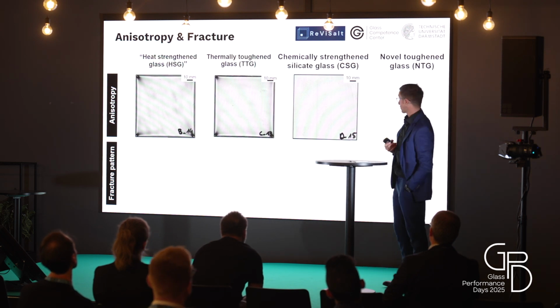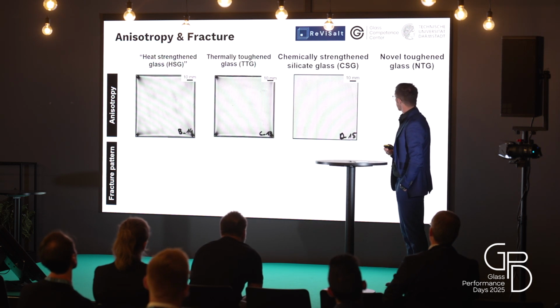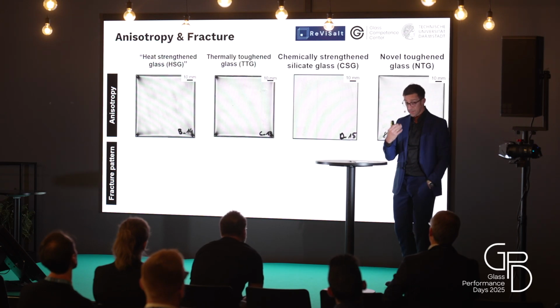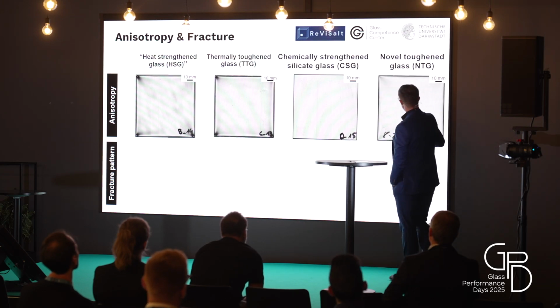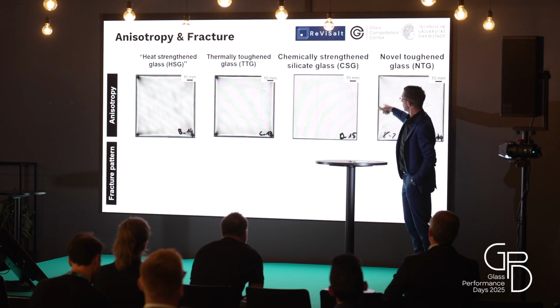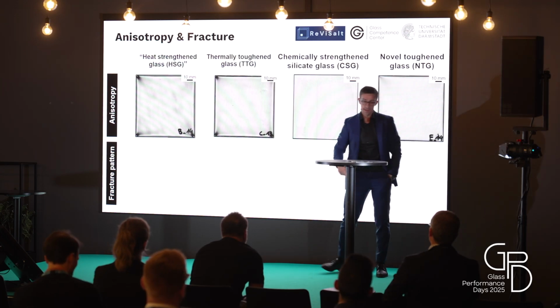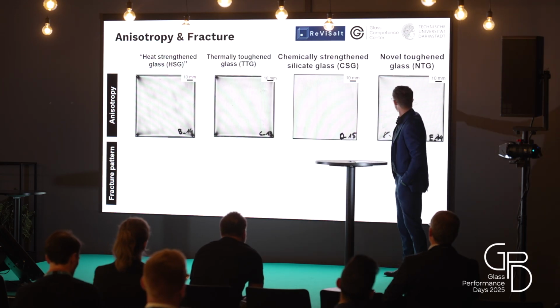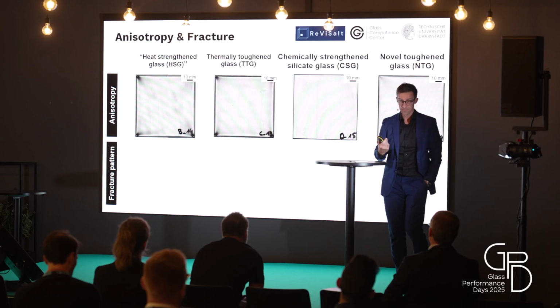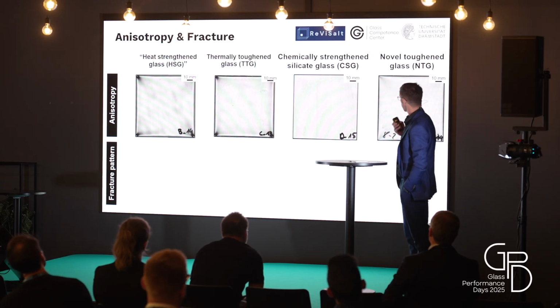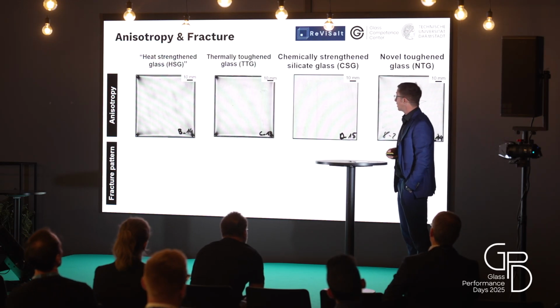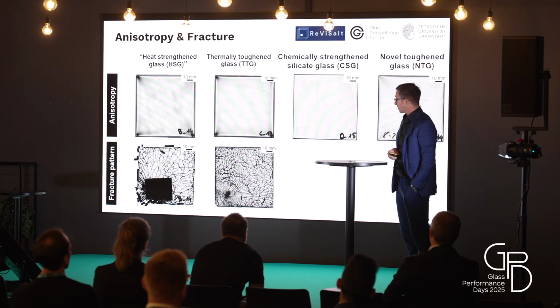No anisotropic effects. And now the novel one, it's a mixture between. We had here near the corners also the same as this, but not too much. And we see here in the field region more or less nothing. No anisotropic effects in the field region. This is pretty cool. Let's go to the fracture pattern.